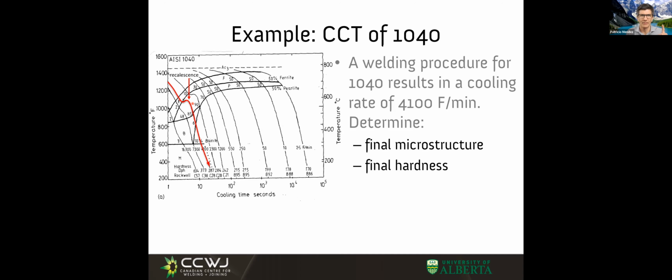That's quite paradoxical. And what happens is you start to take heat out of the sample, and the sample comes down in temperature until there is a transformation and all that heat gets released. This is called recalescence. And it's such an amazingly cool thing to see. We had one of the guys in the lab do a whole PhD in measuring this recalescence. And from the recalescence, you can reconstruct the phase transformations. So although it looks like just a bump and an annoyance in these diagrams, there is so much information here.